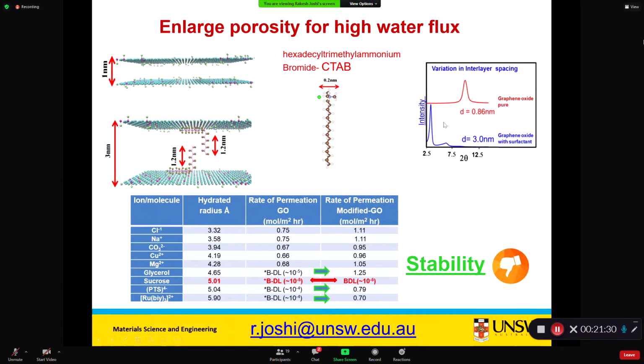Here you see the intrinsic interlayer distance for graphene oxide, which is 0.86 nanometer. In graphene oxide, the interlayer distance is the porosity of the membrane. With surfactant we could change it, up to 3 nanometer. We know this is not going to block smaller ions, but we thought we could still block larger molecules and at the same time have higher water flux. These membranes showed good results, but the stability was a bit questionable. So we didn't continue that project of using surfactant-modified graphene oxide membranes.